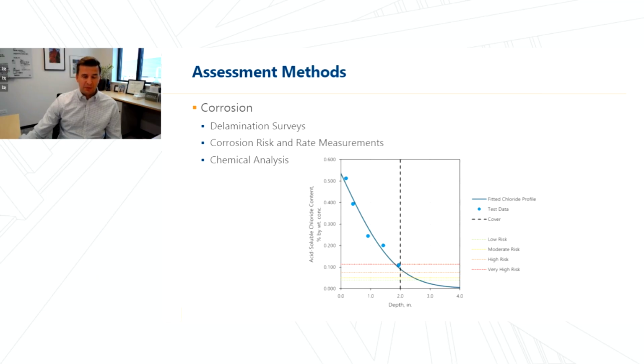I'd also like to add that, especially in corrosion considerations, we lean heavily on chemical analysis. For example, we would want to quantify the chloride concentrations over the depth of the concrete from the surface, and that's what we have shown here in this example, a chloride profile measured from the surface of the concrete.